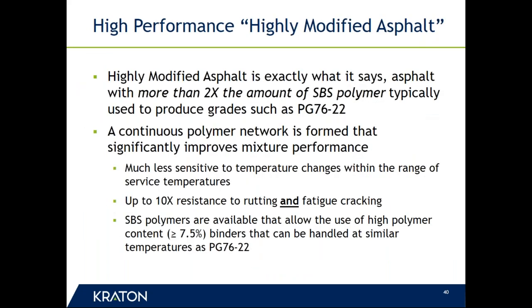And what that's led to is what we call highly modified asphalts, or high performance grade asphalt binders, as we're introducing or trying to introduce here into Texas now. In this case, you're looking at something on the order of around 7.5%, which is usually more than double the amount of SBS polymer used to make grades such as 76-22. But most importantly, and we'll get into detail on this during the next program, the level of benefit you get from this is perhaps greater than you get going from 64-22 to 76-22.